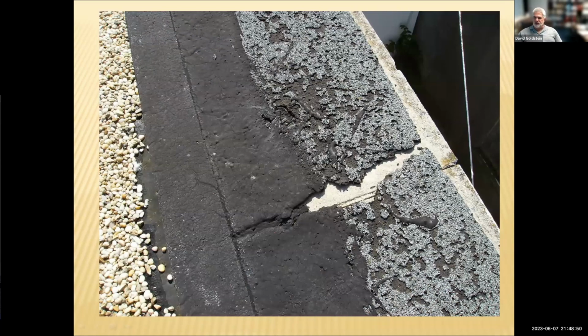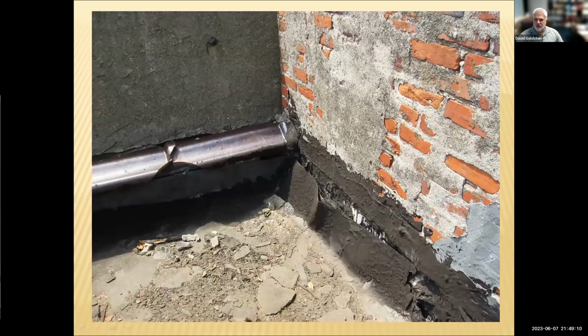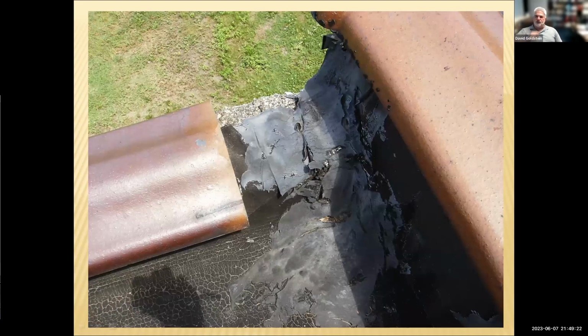Long deteriorated. This is a built-up roof, or excuse me, not built up. This is a single-ply membrane that's on here, and it's weathered and aged so that it's almost not even there. Parts of it have fallen off and weathered drastically. No cant strip. When they went from the horizontal to the vertical, this is where it has the ability to tear off pretty easily. Excuse me. Look at the openings and the coping for drainage.